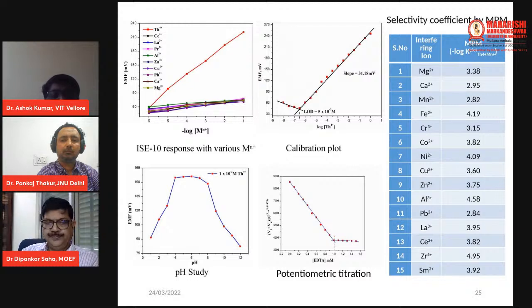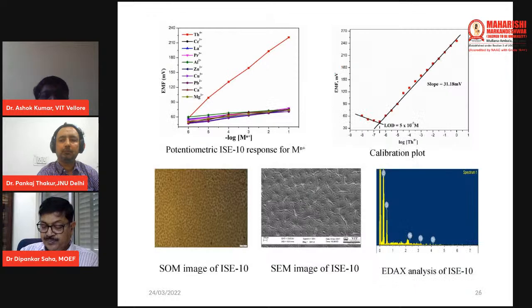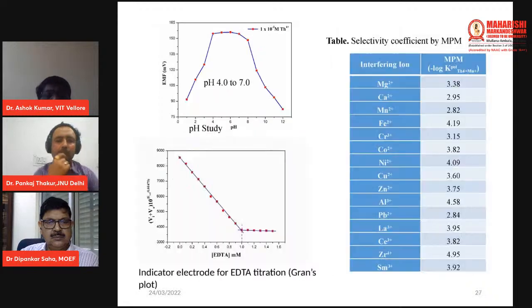Any electrode, if you are able to use it as an indicator electrode, that makes it robust. Also, we studied the interference effect using the selectivity coefficient values. If you see, all the selectivity coefficient values are high and positive, which are welcome values with respect to a sensor. We also studied SEM morphology, which helps show how the morphology changes after the complex formation.